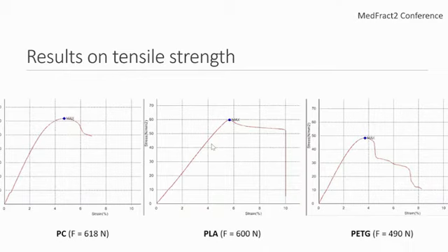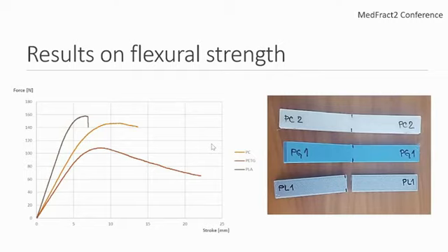And these are the stress-strain diagrams. I will go fast in the interest of time. These are the results of the flexural strength. Again, the PLA is completely broken, and PETG and PC have plastic deformation, which again shows that the PLA is very rigid compared to the other two materials, which have more flexibility.